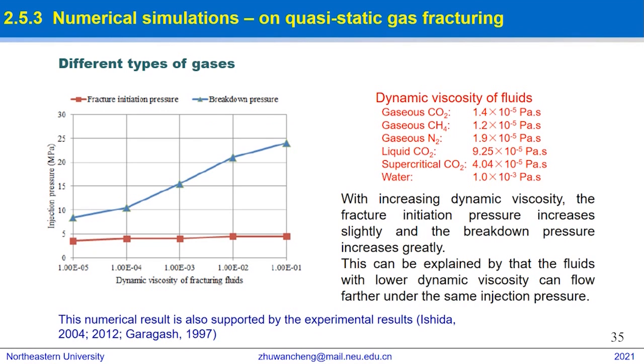The fracture initiation pressure increases slightly, and the breakdown pressure increases greatly. This can be explained by the fact that fluids with lower dynamic viscosity can flow farther under the same injection pressure. This numerical result is also supported by the experimental results by Ishida and Garagash.